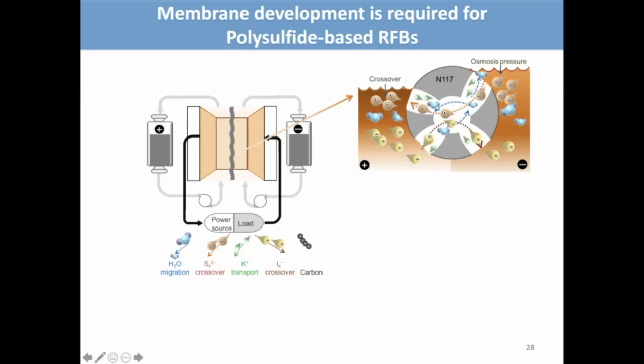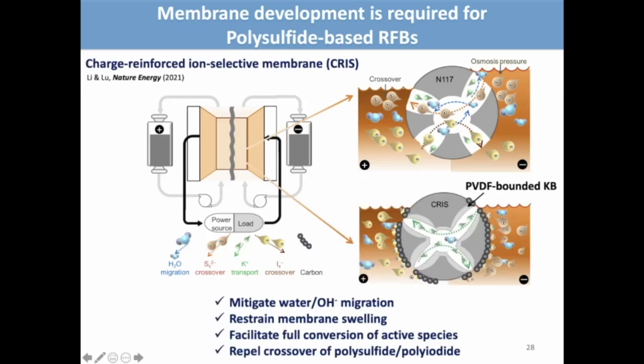First is the crossover of polysulfide and polyiodide across the membrane, and this will lead to capacity loss. This capacity loss is essentially irrecoverable. And second is water migration and also OH migration through the membrane due to the osmotic pressure. So this becomes a critical issue if you want to pursue a polysulfide-based redox flow battery. So recently, we developed a new membrane to help mitigate these types of problems.